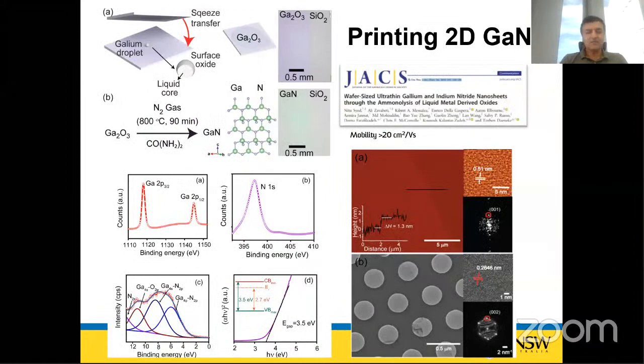It's very interesting for other oxides or other materials too. For instance, this is the example of gallium oxide. We harvest gallium oxide on the surface. You can use gallium oxide directly for making transistors. Gallium oxide can be used for high power transistors, or you can do a second processing step. Here we expose it to a precursor of nitrogen like urea at very high temperature, and we produce gallium nitride. As you may know, gallium nitride is a very famous semiconductor for making blue LEDs. Blue LEDs are used in low energy lamps all over the world because the mobility is very high, 20 centimeter squared per volt second. Band gap is 3.5 eV. This is actually a very high quality material. We can make LEDs. It's commercially in use now.